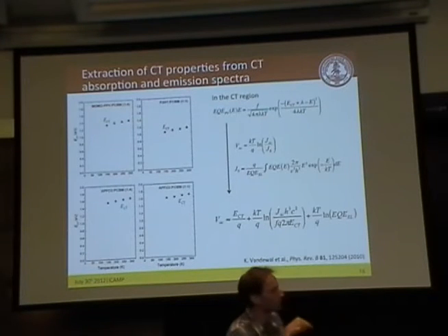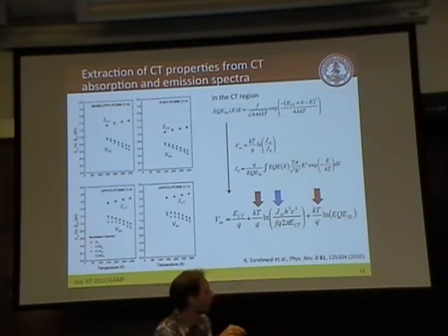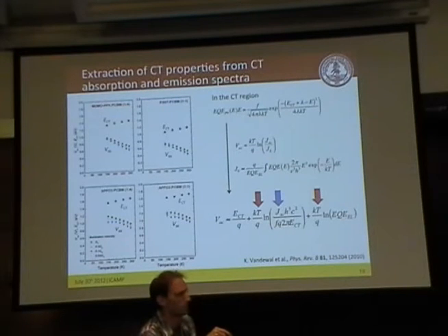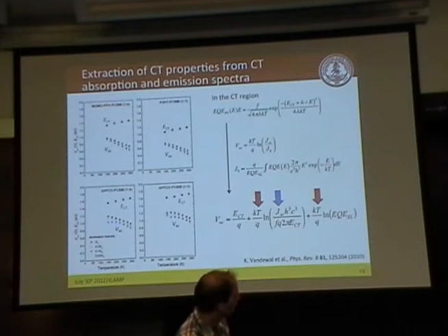The first thing you notice is that there's a temperature dependent part, and a light intensity dependent part, or a part dependent on how much current at short circuit comes out. So let's look at the temperature dependent part. If we lower the temperature, VOC should rise. Yeah, that's what happens.